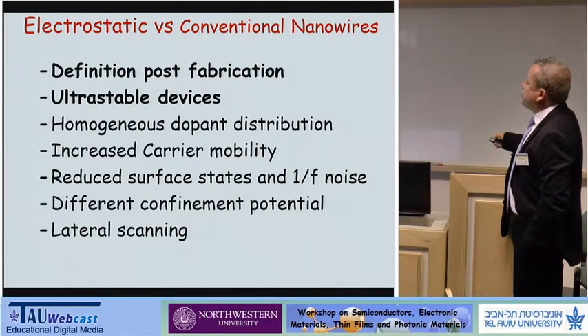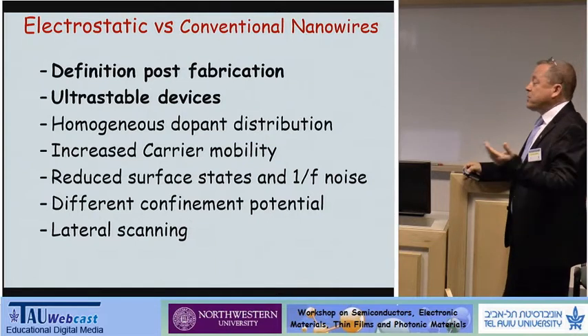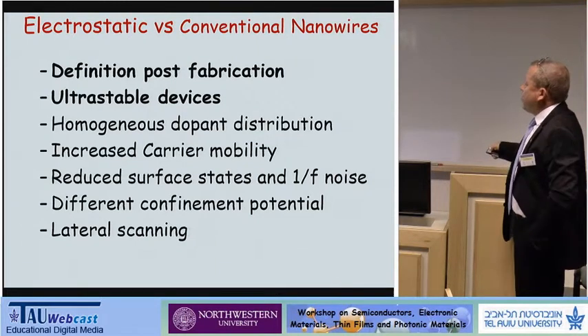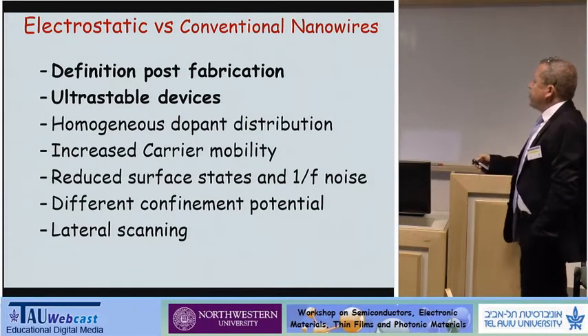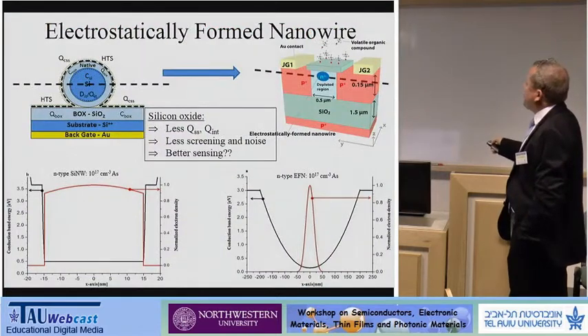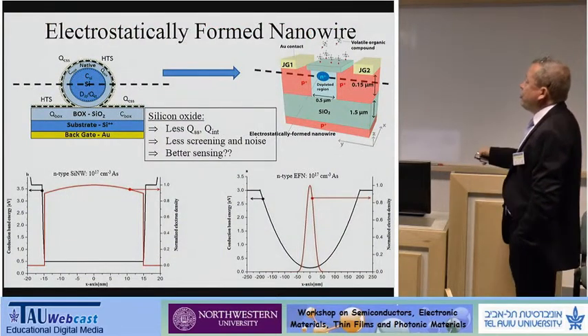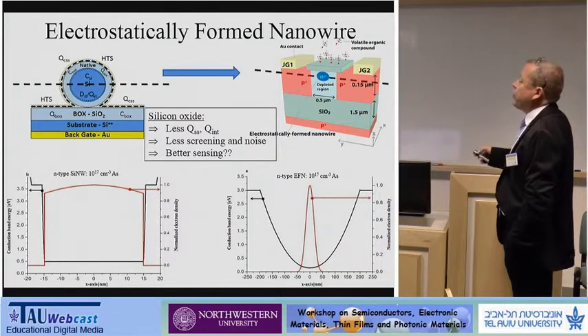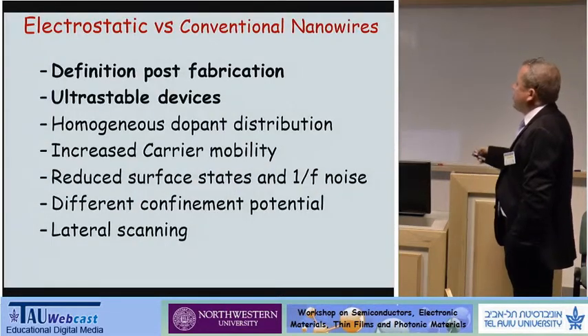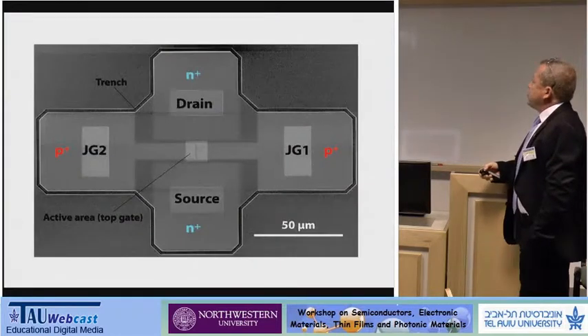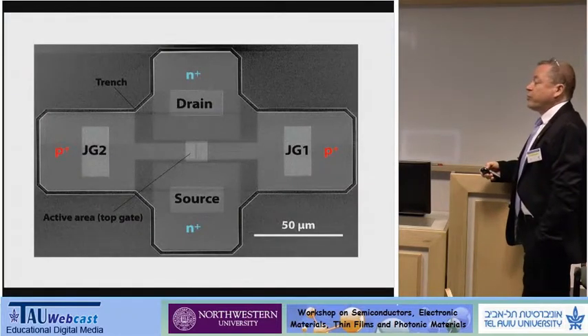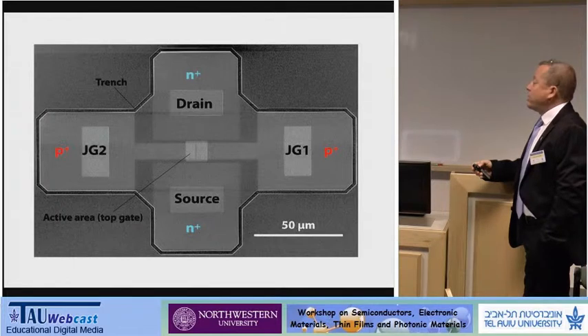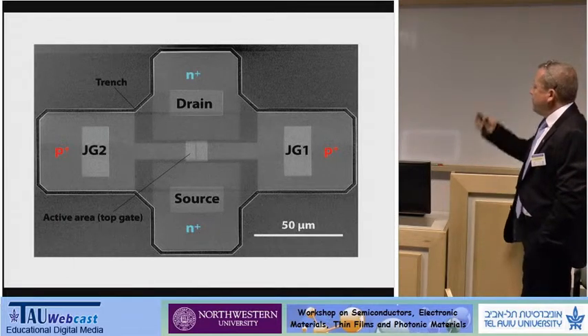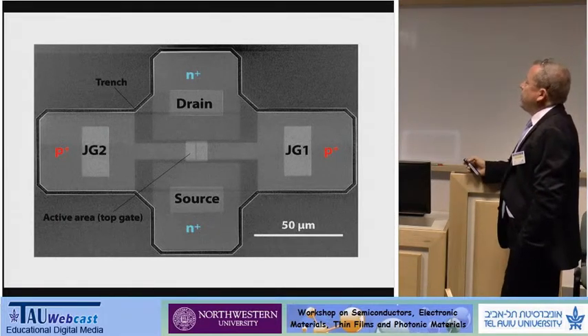It has homogeneous dopant distribution because this is bulk silicon. Increased carrier mobility, again, because it has a perfect passivation here at the top, not like here. These nanowires are very difficult to passivate. Reduced surface states and 1/f noise, and other advantages. So this is the second generation of the devices. All the devices are produced in Tower Jazz. This is a fab in the northern part of Israel.